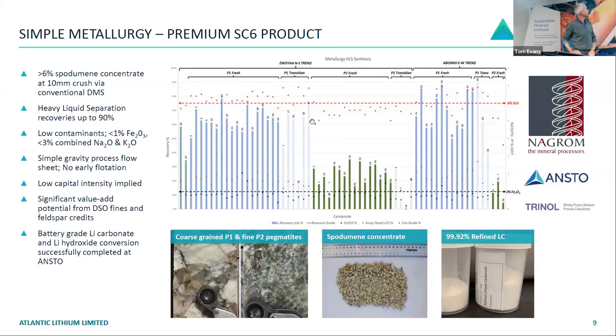And on average in the P1s, you're looking here at that 70%, but up to 90% recovery, and you're producing from a head grade, which is your brown dot here, of around about 1.5%, and up to 2%, you're getting up to a 6% concentrate easily, the red dots, that red line is 6% lithium oxide. And importantly, we also look at our iron concentration within that concentrate. You want that iron to be below a percent.